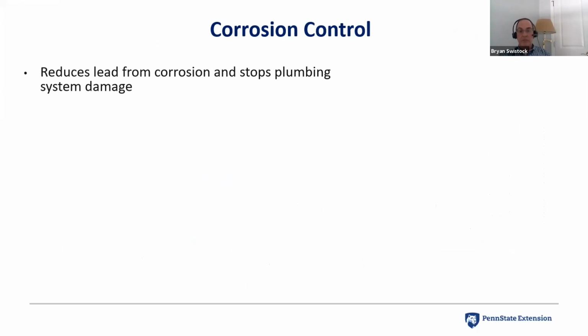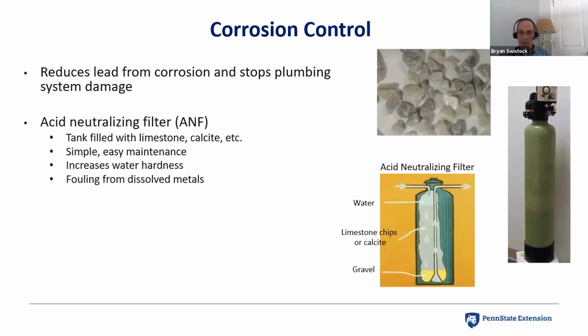We can reduce lead by reducing the corrosion and stopping the plumbing corrosion from occurring. The classic way of doing that is with an acid neutralizing filter, which is typically just a big tank filled up with calcite or limestone chips, some sort of alkaline material that the water trickles through. It dissolves that material and it raises the pH, raises the alkalinity and the hardness, and reduces the corrosivity of that water. So it's a very simple treatment device.